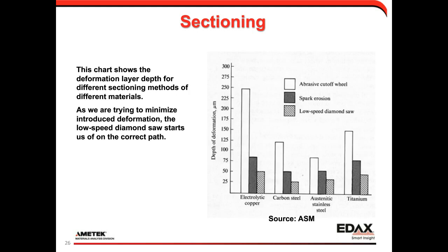And this is just a little schematic. This is from the ASM handbook, where it shows the depth of deformation introduced with an abrasive cutoff wheel and also with a low-speed diamond saw. And you can see that in cases of these different materials, we have copper, a couple of different steels, and titanium, the diamond saw introduces the minimal amount of deformation.